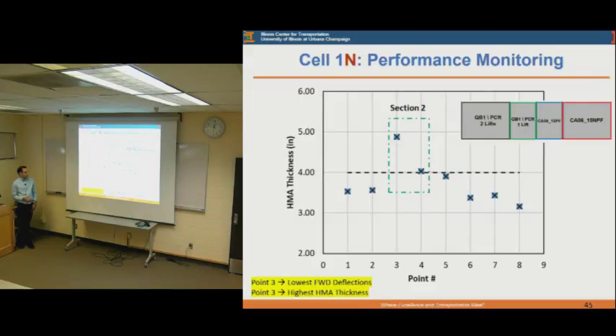This is showing the cores which we recently obtained from the test sections and how the HMA thickness is varying on top of these test sections at the different measuring points. Keep in mind that each 2 measuring points are 1 section, so this is section 1, section 2, section 3, and section 4. And as you can see here, section 2 had the highest HMA thickness, while section 4 had almost the lowest. And there was quite a big variation between 3 inches and 5 inches at some point, while in most of the points it was between 3 1/4 and 4 inches, which was the target HMA thickness. So this explains that some of the variation between the test sections is actually due to the difference in the thickness of the HMA on top of these sections.